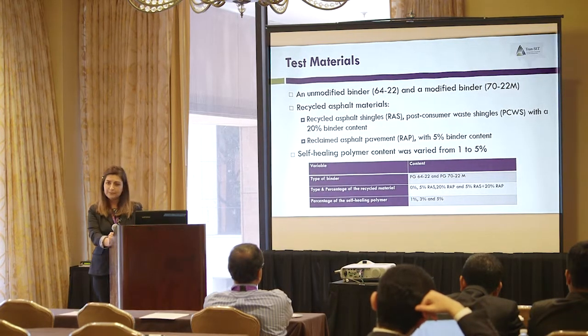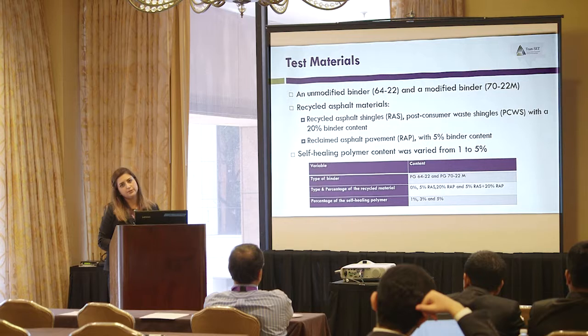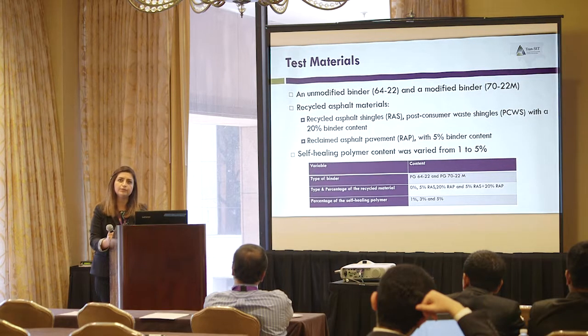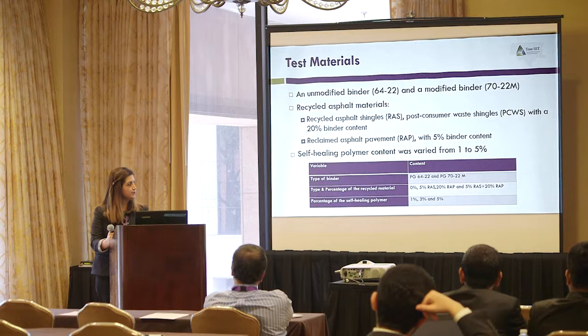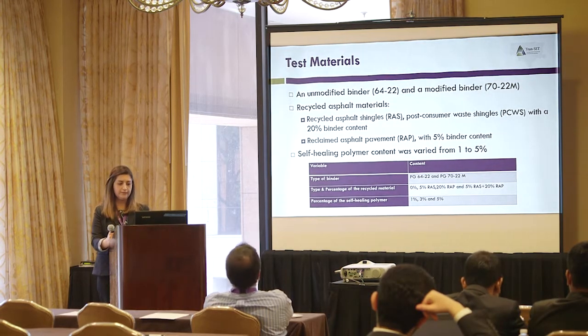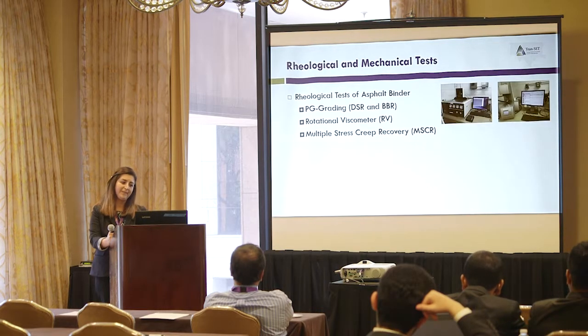We added self-healing polymer in 3 different percentages, 1%, 3%, and 5%. And also, we used 2 different UV exposures for the binder blends that we prepared. We exposed the binder blends to 1 hour of UV exposure and 48 hours of UV exposure. And then for the mixture samples, we exposed them to 48 hours of UV exposure.